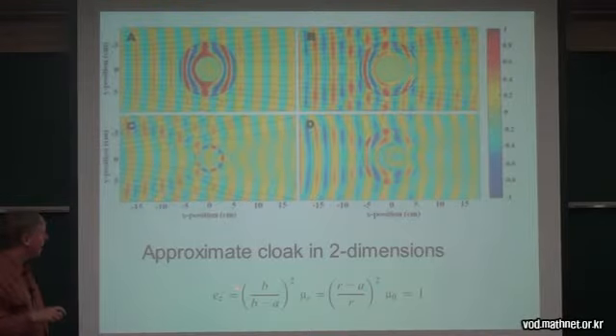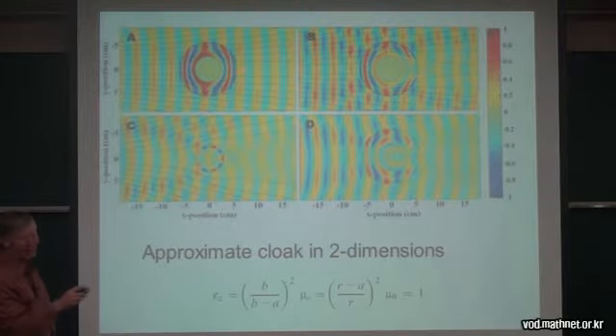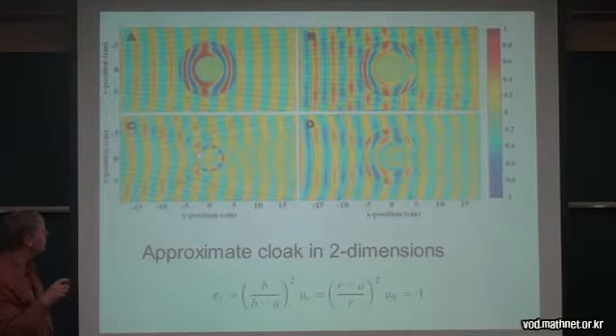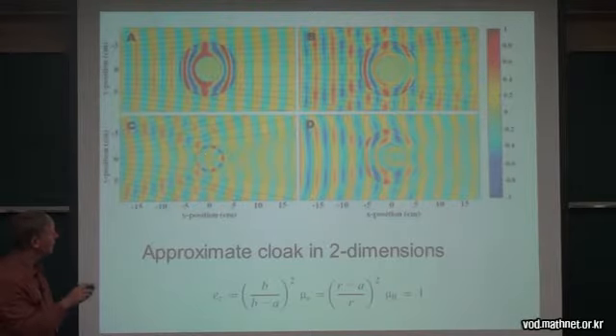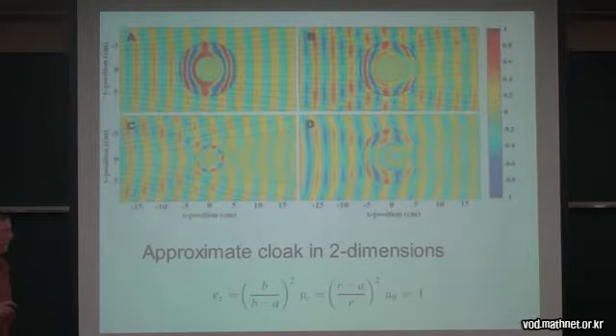And their approximate cloak had electrical permittivity given by this and magnetic permeability given by this. And this is the numerical simulations, so it doesn't behave perfectly anymore. And in particular, there's a little bit of a shadow zone there and reflections in this direction here. But these are the experimental results, which are meant to be compared with this one here. And the waves actually pass quite through, as opposed to when the cloak is absent. And these are the experimental results where you end up with much more scattering and more of a shadow zone behind the object.